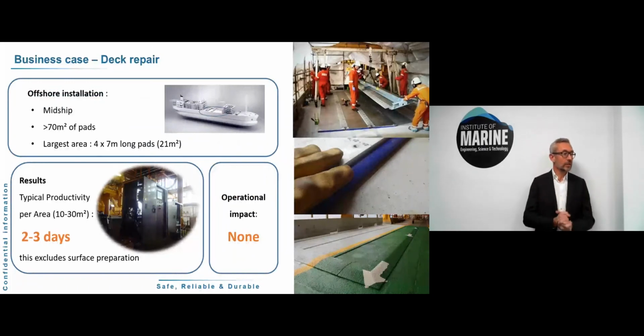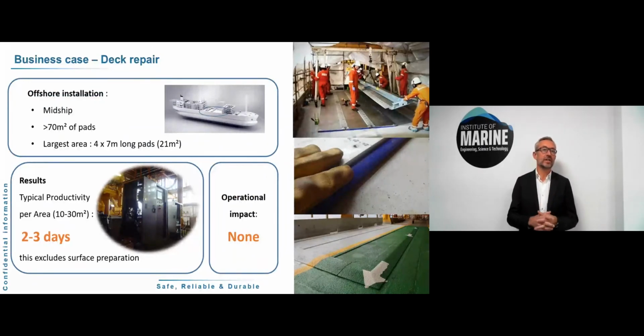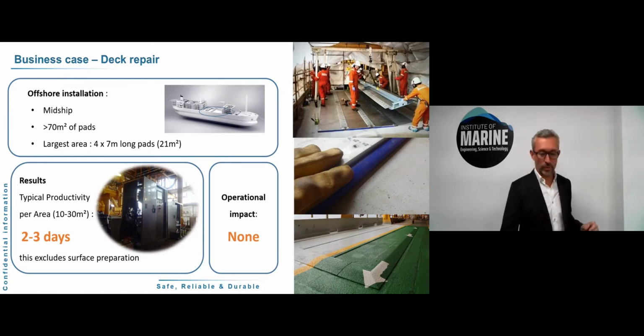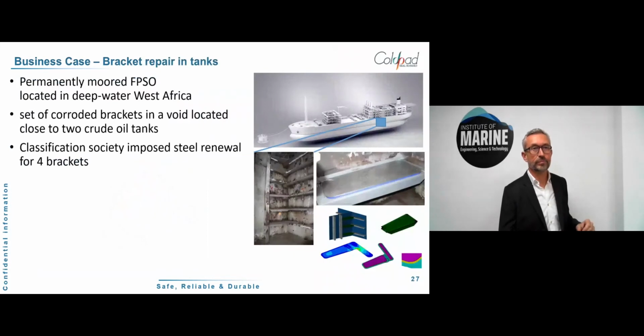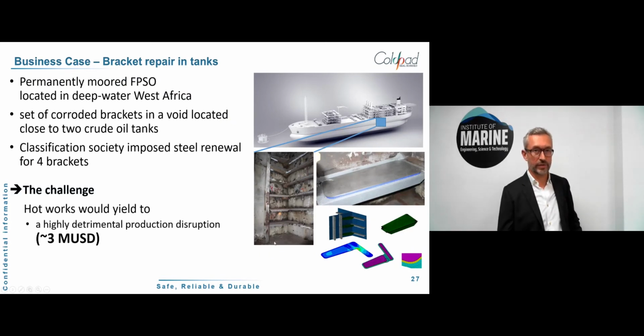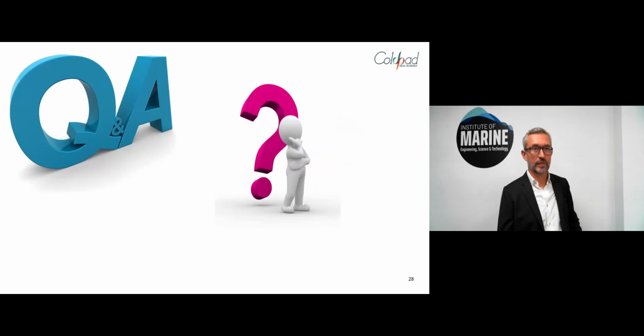To give you an order of magnitude, for a campaign, in one rotation we can install something like 70 square meters, with the largest area to be treated being about 20 square meters. Typical productivity is about 3 days for an area, without including surface preparation. Another example: bracket repair in West Africa for an FPSO. We managed also to avoid production loss.